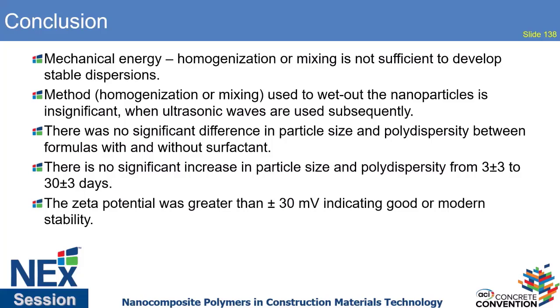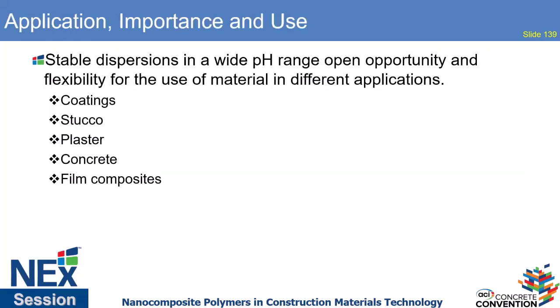Typically, when we work with the zeta potential, one other thing I wanted to mention is that with the electrophoretic measurement, we also need to establish the pH at which the zeta potential will be 0, because at that pH there are no repulsive forces. So for different materials it will be different. For example, with something like silica, you can get a very stable system at a lower zeta potential, but for something like titanium dioxide, you probably need somewhere above 50 or even 60 millivolts, plus or minus absolute, to get a stable solution, or nano dispersions.